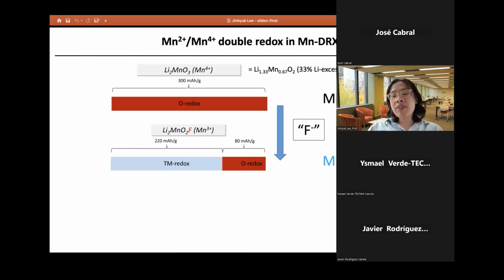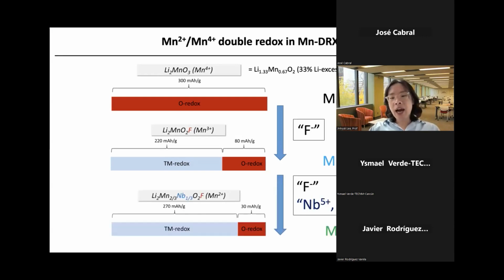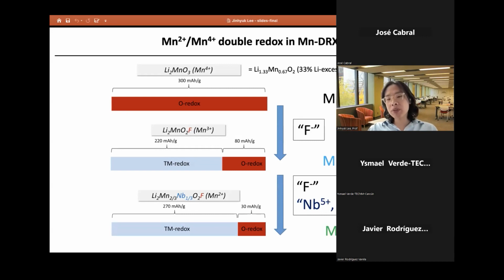But we can do this even further by substituting some of the manganese 3+ cations with high valent cations such as niobium 5+ and titanium 4+. Because if you include such high valent cations, the remaining cations, including manganese, have to decrease their oxidation state. So with this particular composition, you can push the manganese oxidation state from 3+ to 2+. In this case, the manganese starts from manganese 2+. So if you charge this cathode, you can extract 2 electrons from this manganese 2+ to manganese 4+ double redox couple, right?